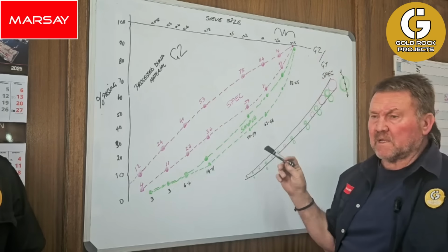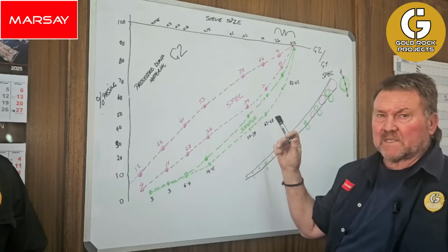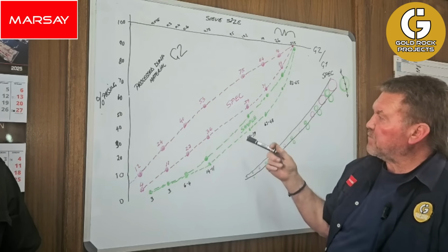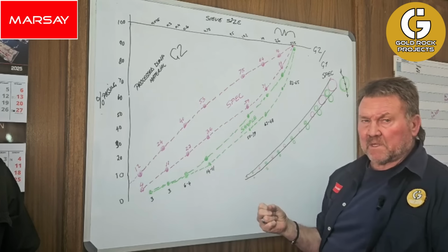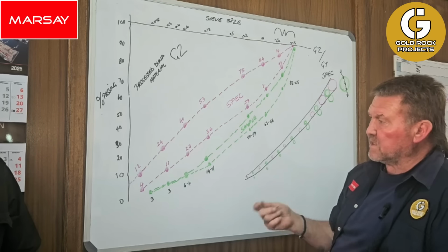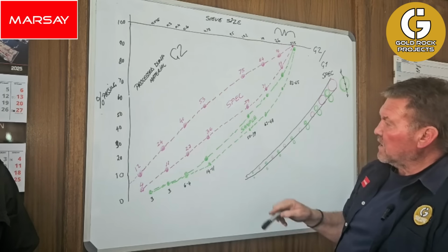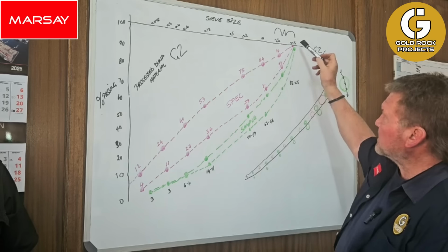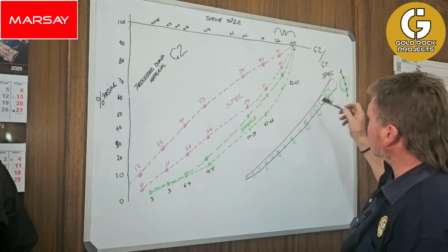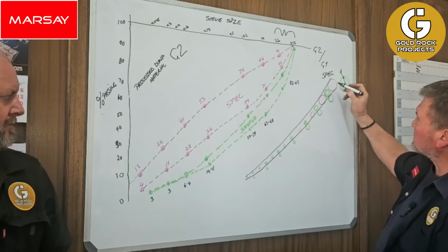Now, what has happened here? It was a recycled or processed dump already, which, what I can see from here, is that a lot of the fines were extracted from the material, maybe used for something or in the process, whatever they were doing. So the only way you could get the sample back is, we've said, take some of the coarse material, crush it. In other words, what we're sitting with is this grading here.